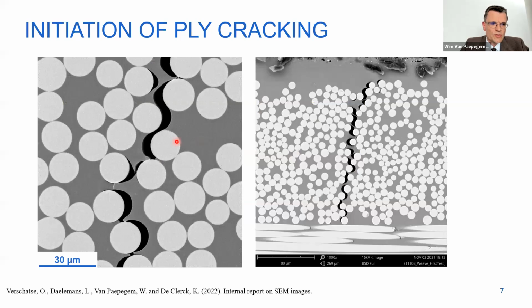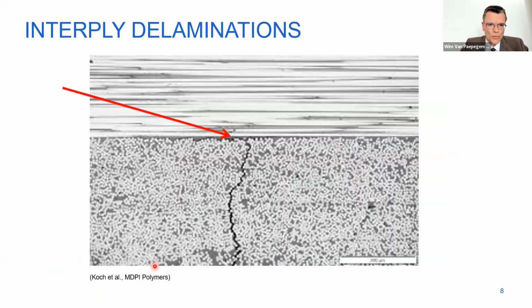Like some of you will know already, typically when you have transverse loading, in this case transverse tension, damage can start very early with disbonds in the fiber matrix interface. And by the way, a beautiful picture from Olivier from our department, where you see the disbonds that then coalesce together. And if you then zoom out, you start to see a ply crack. And when that ply crack meets the boundary with a differently oriented layer, you might get delaminations. Here from Ilya Koch's group, you see a picture where at the crack tip, the crack deflects and you get a delamination. It can also happen at free edges or at rivet holes or in adhesive joints, you can have these delaminations.